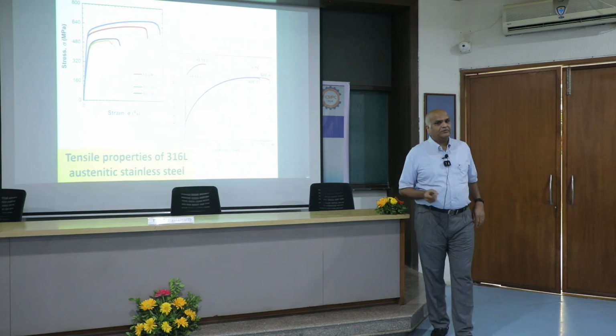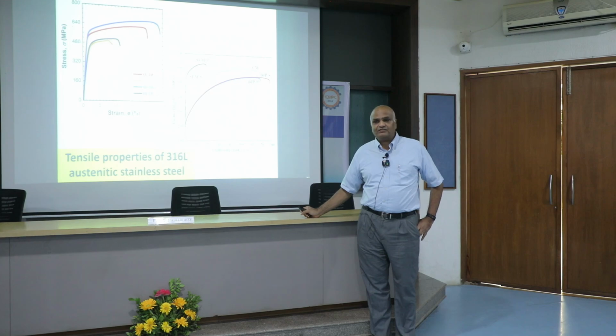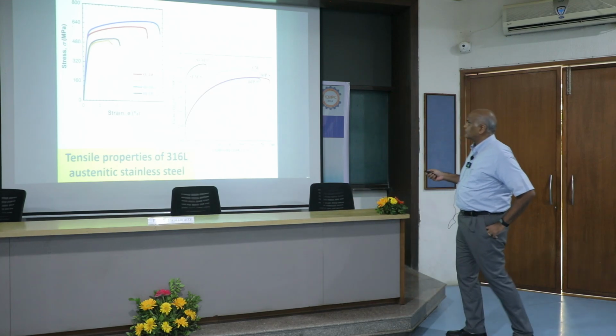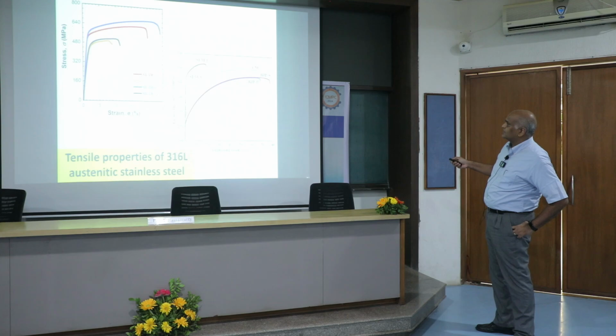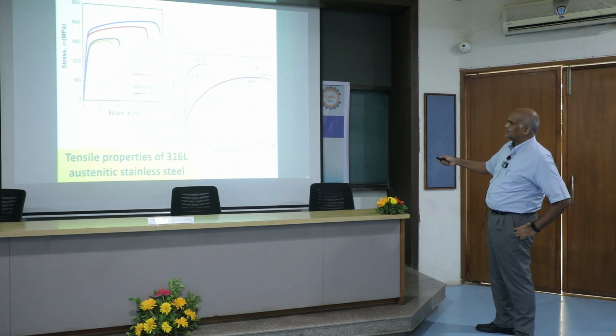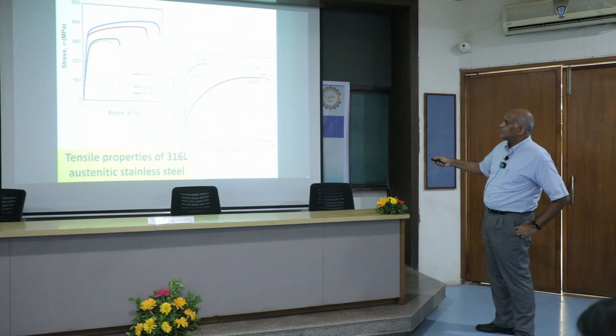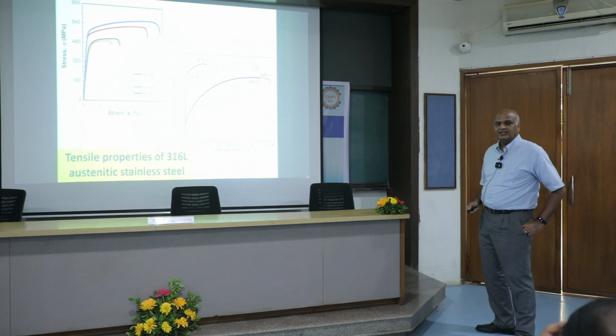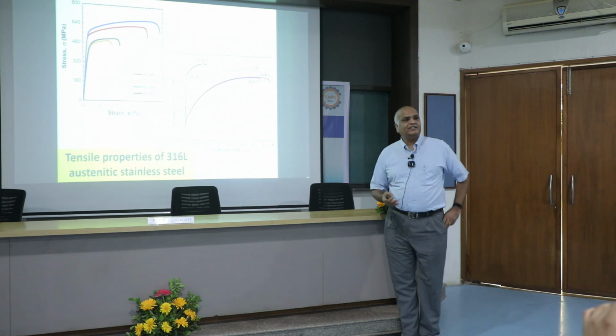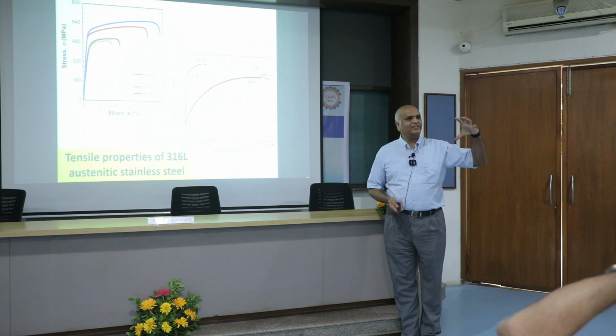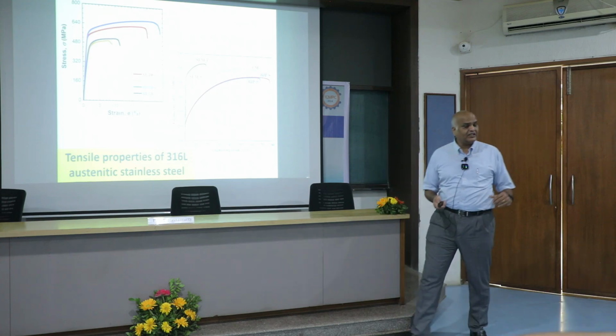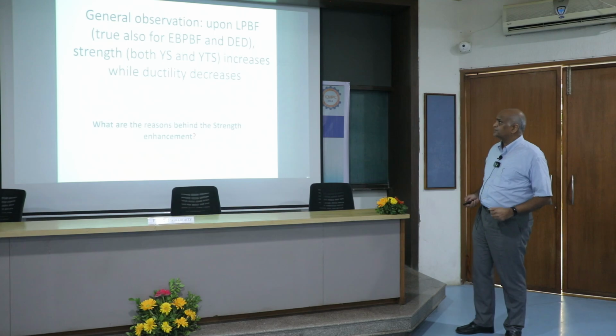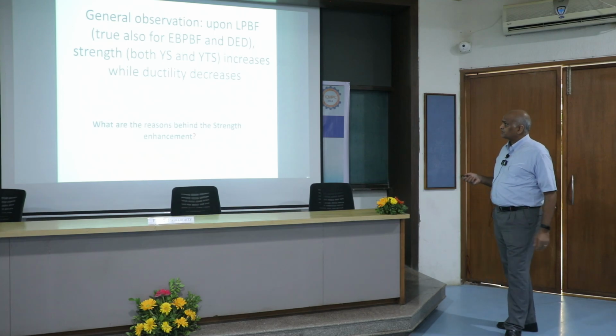No, it's also true for austenitic stainless steel 316L, which is very widely used. So for example, look at this here. The green is conventionally manufactured. You see somewhere around 250 is the yield strength. It work hardens a lot and fails at 600. If this is selectively laser melted, or LPBF, you see the yield strength is much higher, and there is some anisotropy. So the bottom line is that strength goes up and ductility comes down when you 3D print the alloy compared to the conventionally manufactured alloy. Okay, so this is the general observation.